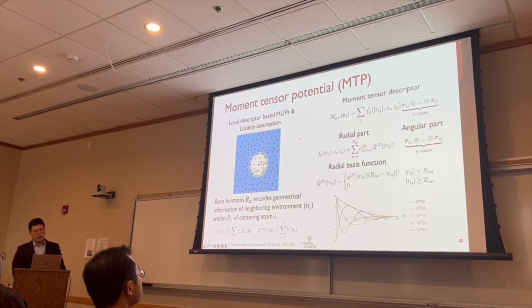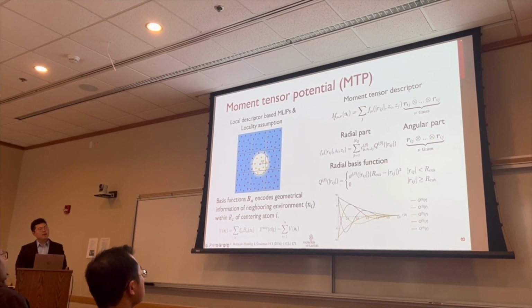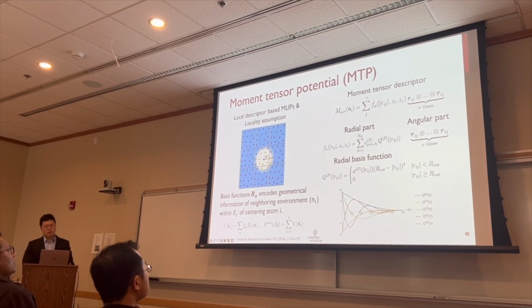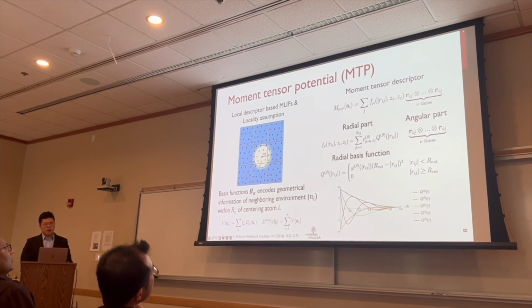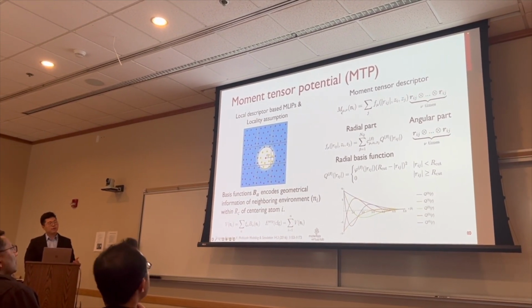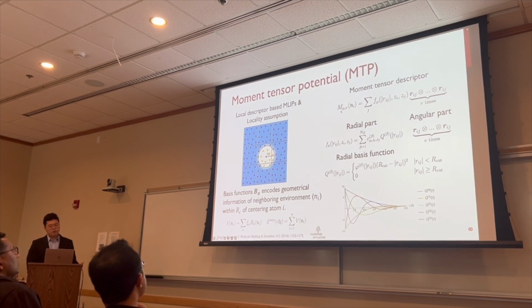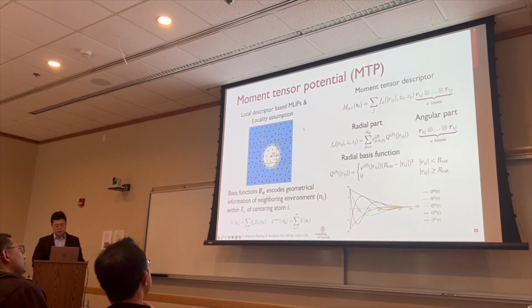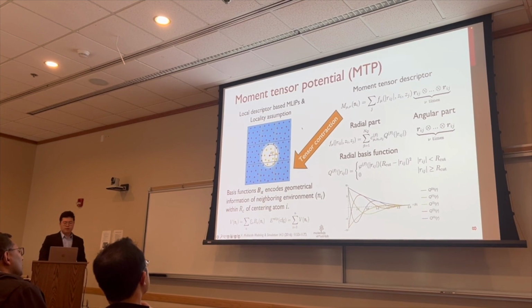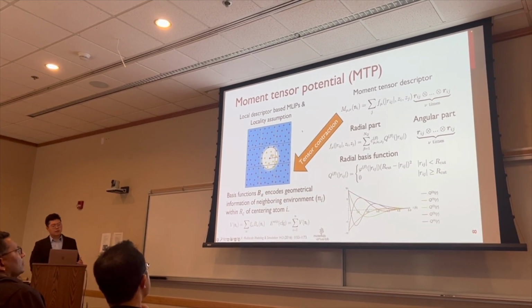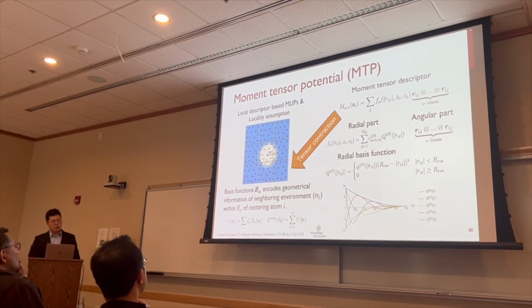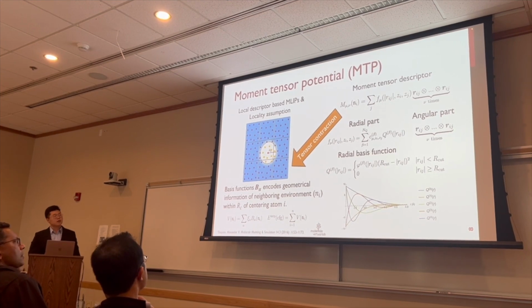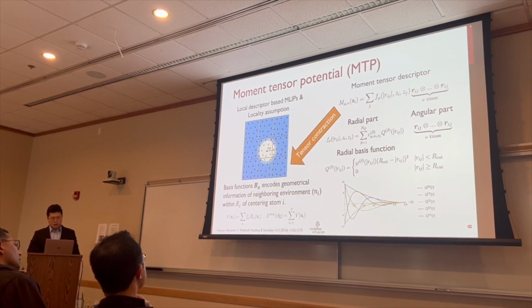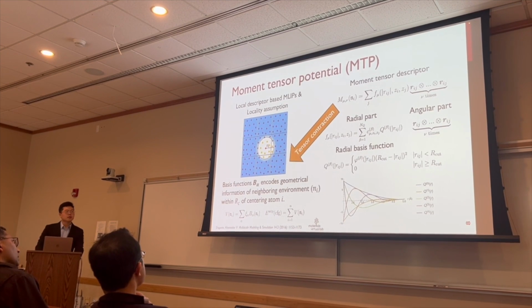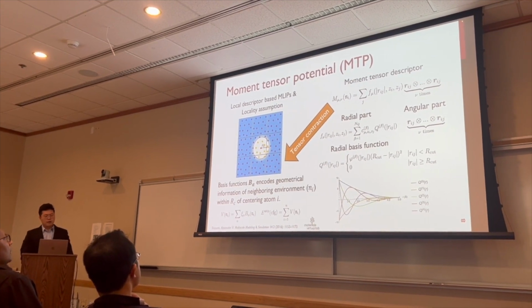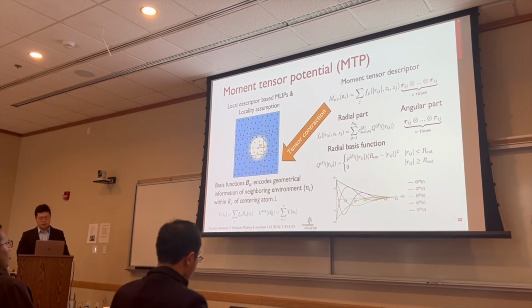So later on, you can imagine that for each atom, it has a set of different moment tensor features from these descriptors. And those different features differ because they have different values of mu and nu. And then a tensor contraction is performed on this set of descriptors to get the scalar basis functions, the alpha. So that's how MTP defines the local environment descriptor and expresses the total energy of a system.